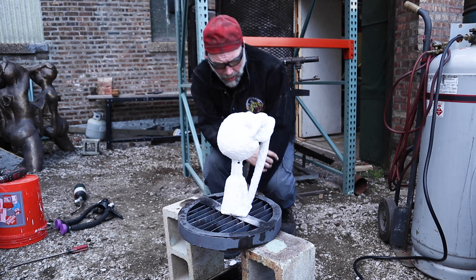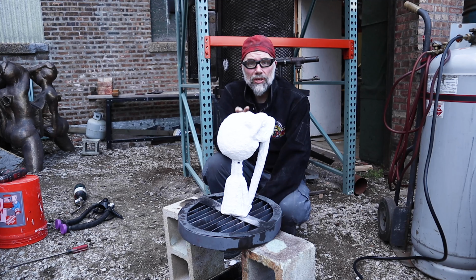Now you might be asking, why not always burn your shells out this way? Why need a kiln? Well, ultimately a kiln is going to give you a lot better consistency. Whereas it looks like, at least initially, that I have a pretty good burn on this shell, 9 out of 10 times if you do this technique, you're probably going to crack your shell. And so that would certainly be the argument for having a burnout kiln or a better situation to more consistently burn out your shells.